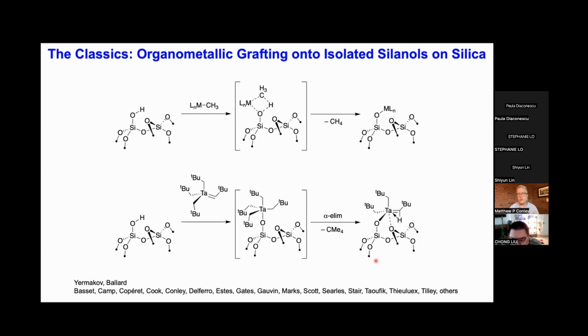So these are sort of the 2 general grafting mechanisms that we normally think of when we're reacting an organometallic with an oxide surface. So then characterization is really the name of the game here. Now you'll notice I'm kind of drawing silica in two different coordination modes. If we reduce this to the sort of MLX conventions, this would be silica acting like an X-type ligand, and this is silica acting like an X-type ligand through the siloxide group and an L-type ligand through this dative interaction between a nearby siloxane bridge and the metal.